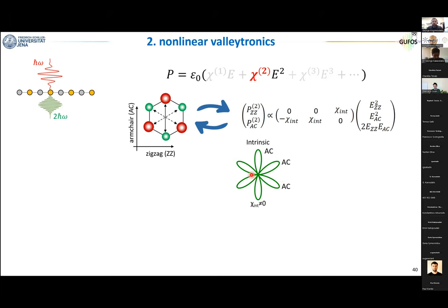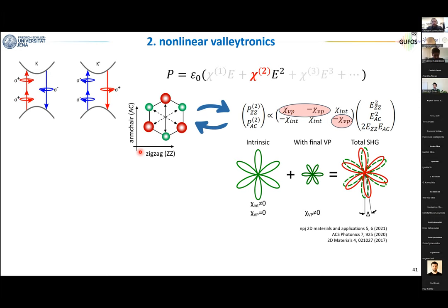So you always measure a second harmonic that is parallel to the input. Now this graph tells you that there are three directions of high symmetry that of course are the armchair directions. And this is basically to say that if you excite along the armchair direction, the second harmonic will be emitted along the armchair direction. This is the case where the material is at equilibrium. So there is no valley imbalance, time reversal symmetry is preserved. Now you break time reversal symmetry, you reduce the symmetry of the system, you will have new terms in your nonlinear tensor that we call valley polarization terms.